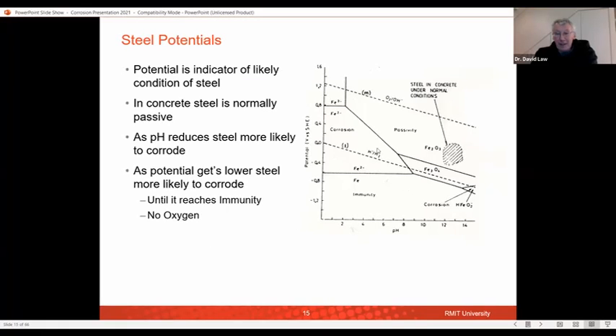And why does it happen? Well, this is a Pourbaix diagram. And when we have our normal concrete and our pH, we are in this pH 10 to 12, 13 zone, and that is where we get passivity. That is, we will have an iron oxide film formed on the surface of our steel, and it will protect our steel because of the pH that we're at.